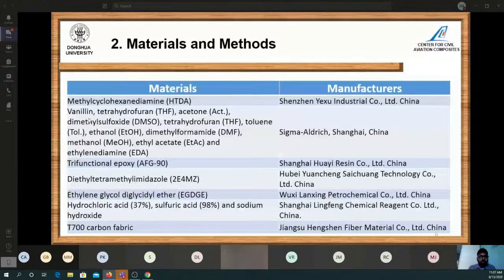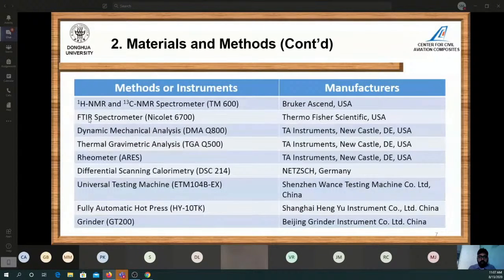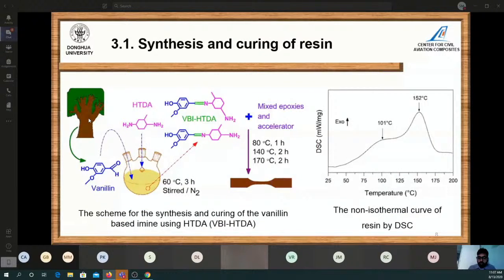So here are the materials that we use for the synthesis of this new structure and new epoxy resin. And these all materials were sourced from China locally, and these are some equipment that we used. So this is the synthesis scheme. We used the vanillin, that was the bio-based and lignin-derived compound, and we reacted it with HTDA, and we produced VBI-HTDA, like vanillin-based imine based on the HTDA.